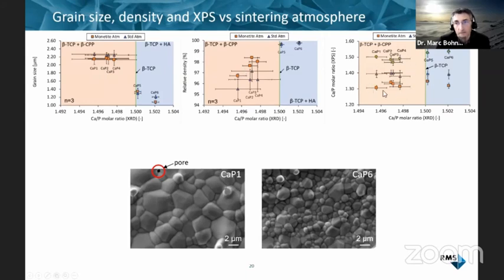And on the right-hand side, I show the composition of the polished sample by XPS. These are the samples that were sintered in a normal atmosphere, so polished. The ratio is slightly below 1.5, but this is normal considering that it's XPS. With this other sintering with monetite, you have a slightly lower value. We still don't really understand why. And if we take these samples and calcine them at 500 degrees, we have a bit of evaporation and formation of calcium oxide, and this leads to this small increase of the calcium to phosphate ratio.